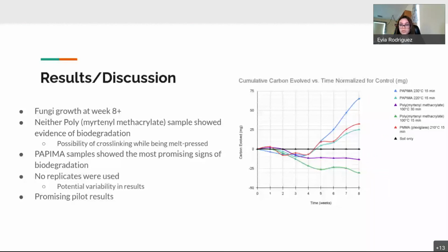The PAPIMA samples, which are the dark blue and the light blue samples, show clear trends of biodegradation since they're above the line of the soil-only sample, and also plexiglass, which is the red line, shows biodegradation. However, both samples of poly(myrtenyl methacrylate) do not show any signs of biodegradation, which means that there's a potential that something happened during the melt pressing process that strengthened the structure of the plastic. So when the plastics were melt pressed, there's a possibility that they're cross-linked, and that would strengthen the structure of the plastics and lead to a slower rate of biodegradation. Furthermore, as I mentioned, there's no replicates of any of the samples used, so there's a lot of variability that could potentially be occurring in these results.